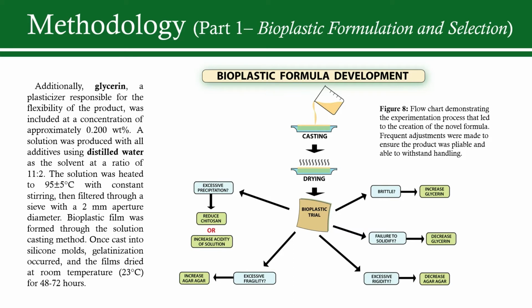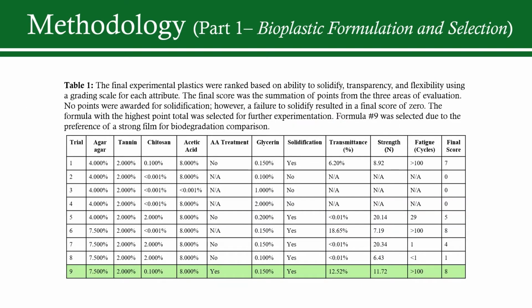Overall, I found that glycerin, a plasticizer, was primarily responsible for the flexibility of the plastic. Agar-agar added stiffness and strength, and chitosan accentuated this strength, but was also responsible for some unwanted precipitation. The levels of acetic acid and tannins remained relatively constant as their concentrations seemed to be effective. The table shows the final 9 formulas examined and the results of the transparency, strength, and fatigue tests. These 3 were conducted to get a general overview of each formula's performance.